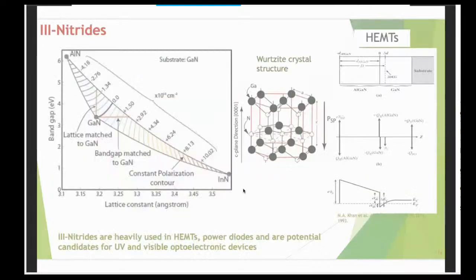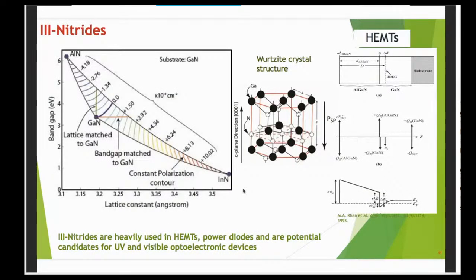So the III-nitrides that I was talking about are really special materials. One reason is that no other family of compound semiconductors has such a large range of band gaps. So right from aluminum nitride, 6.2 electron volts band gap, to gallium nitride, 3.4 electron volts, to indium nitride, which is 0.7 electron volts, we get band gaps that go from deep ultraviolet to infrared region.